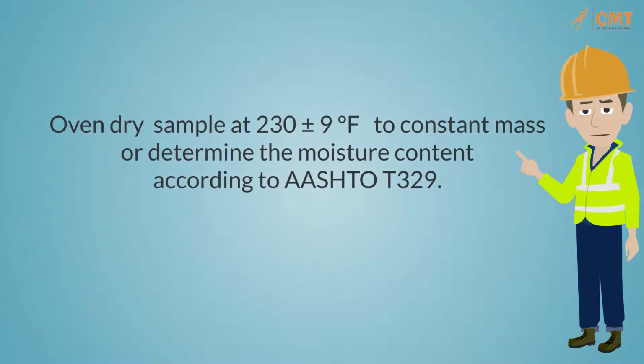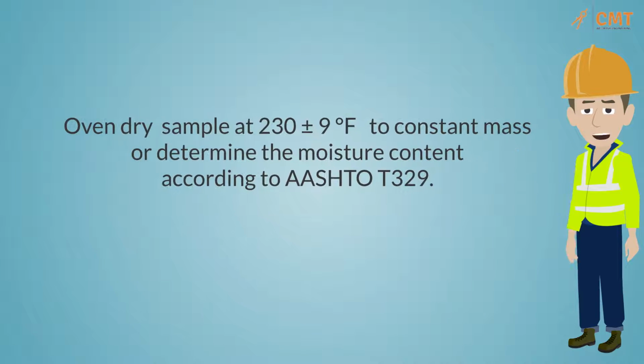Once the oven has reached the chamber set point, you will need to obtain a representative portion of the asphalt mixture and reduce it to the required sample size. Then oven dry the sample at 230 degrees plus or minus 9 degrees Fahrenheit to constant mass prior to testing, or collect a separate representative sample and determine the moisture content according to AASHTO T329.